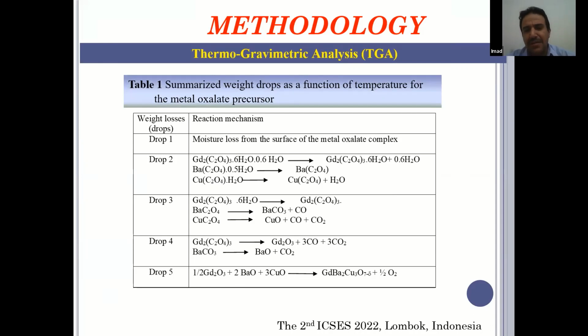For example, dehydration occurred at step 1. In step 2, the water of crystallization is removed, and in drops 3 and 4, the material is converted to oxides and carbonates, and in the final drop, the material is converted into the high temperature superconductor.